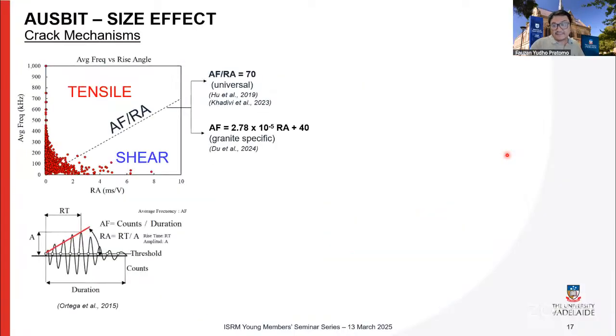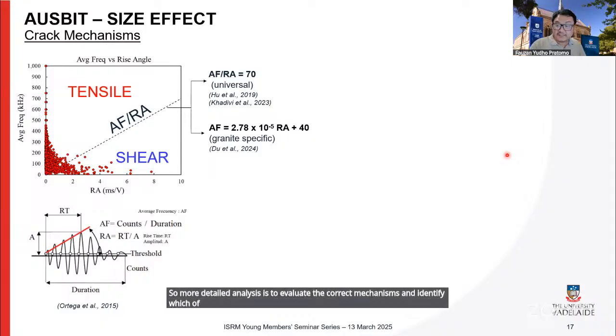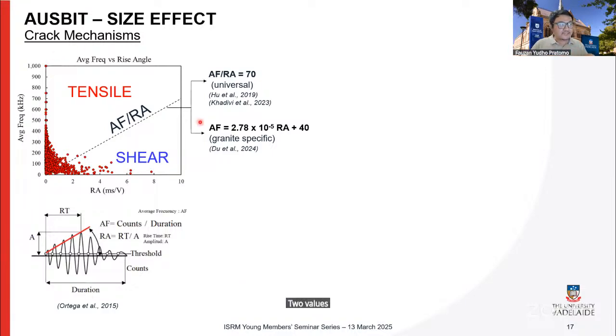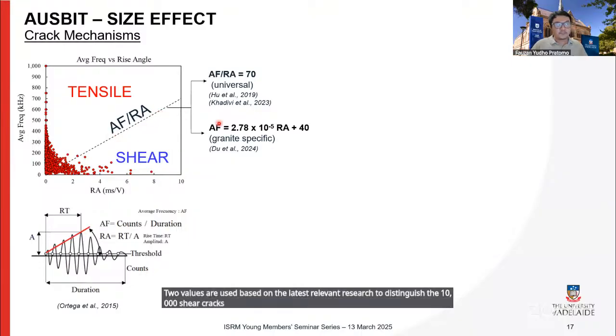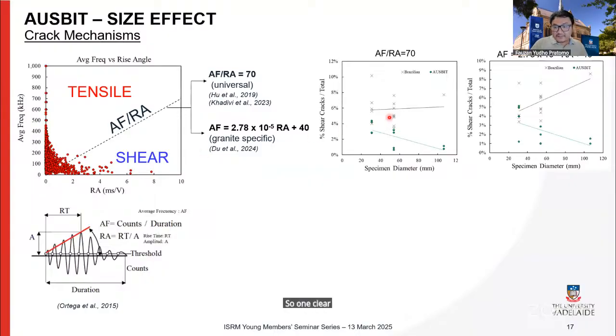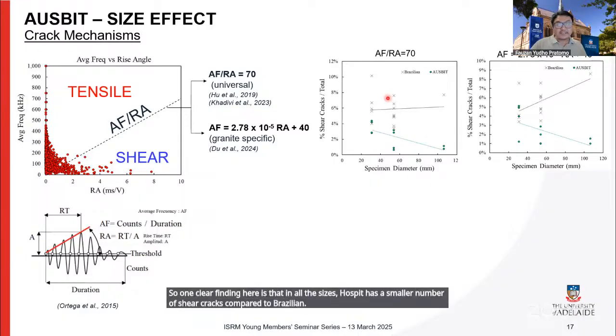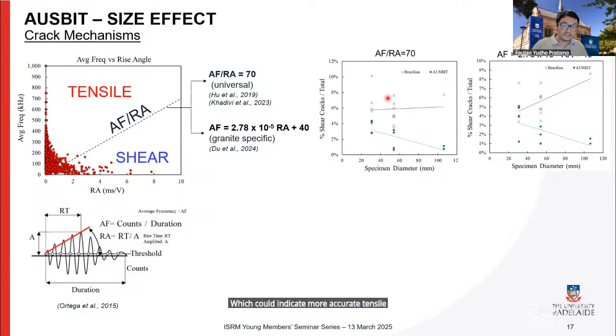More detailed analysis is to evaluate the crack mechanisms and identify which cracks are tensile and which are shear cracks, based on the ratio of the average frequency and the rise angle. Each point here resembles a single acoustic hit. Two values are used, based on the latest relevant research, to distinguish the tensile and shear cracks based on this ratio. One clear finding here is that in all the sizes, AUSBIT has a smaller number of shear cracks compared to Brazilian, which could indicate more accurate tensile behavior compared to the conventional Brazilian test.